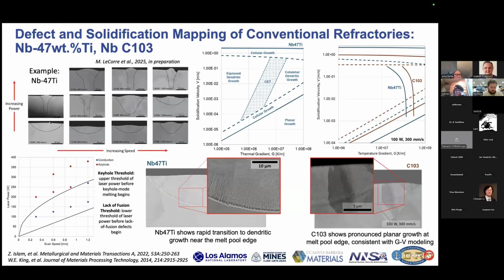And so this is an area we're working a lot more in more recently as well. So moving forward, we've been doing work on refractory alloys. So we started doing work on some conventional refractory alloys, niobium Ti and niobium C103, which is really a baseline refractory alloy. And this work is also in collaboration with Teresa's group at UCSB. But these are some example images of melt pool tracks that we did.